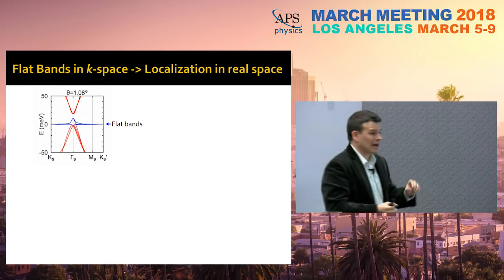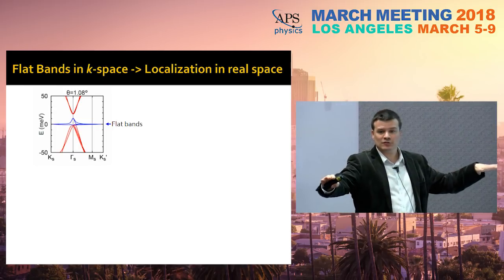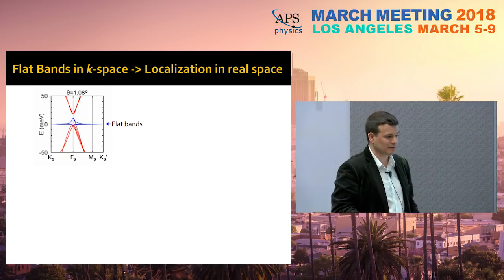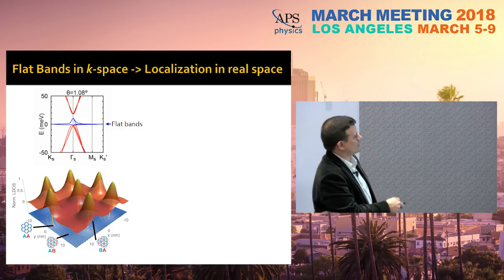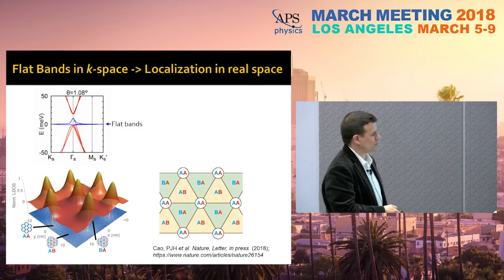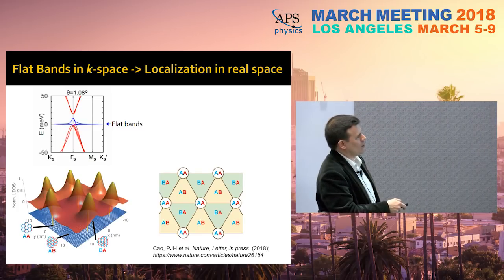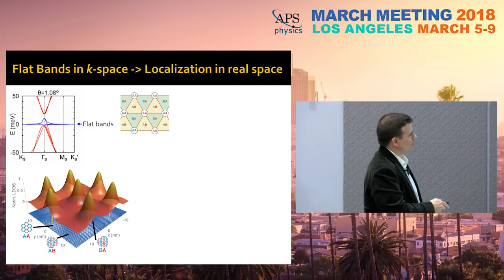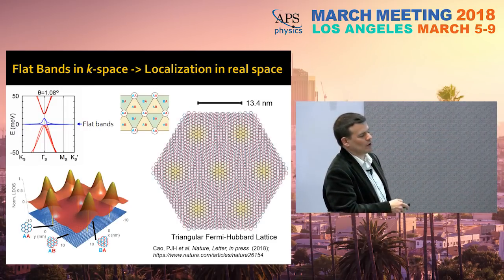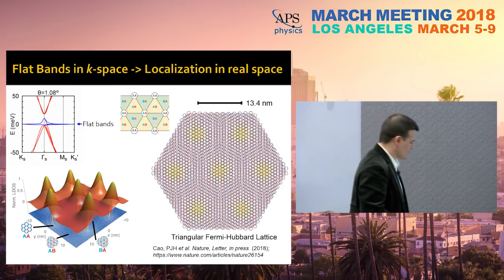Now, flat bands in momentum space mean localization in real space. Here you have the calculated density of states in these flat bands, and it happens that the electrons are concentrated in these AA stacking regions. These regions are weakly tunnel coupled through the AB and BA stacking regions. So what we have here is electrons, which we can load in this superlattice. The separation between these AA regions is 13.4 nanometers. So here you have our triangular Fermi-Hubbard lattice, where we can load electrons and try to play with this. Now let me start showing you some data.